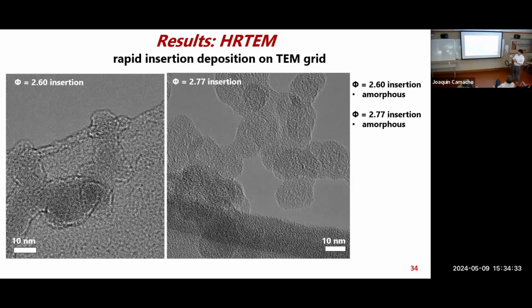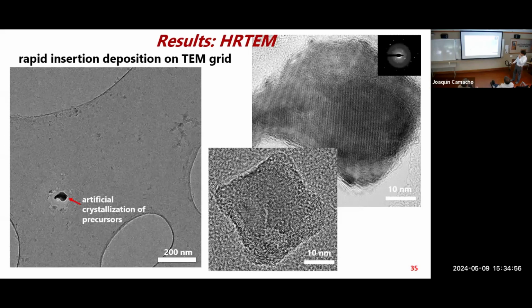But then when we collect over a longer time, we probably see graphene structures that occur from a deposition process over time, because there's so much excess fuel, extra hydrocarbons in the flow. As you deposit over time, they undergo a different process. That's not a flame aerosol process. Okay, so we also see a lot of artifacts when you rapidly insert into the flame, some rapid condensation, quenching process. I'm thinking that this is typical soot, these little soot particles. This is what we are expecting for soot formation.